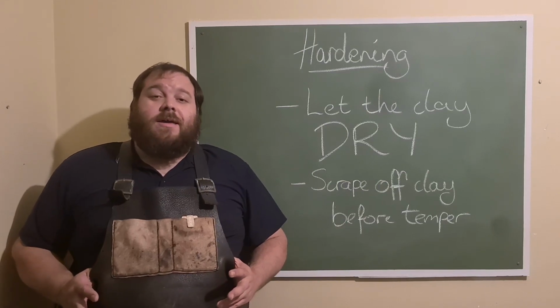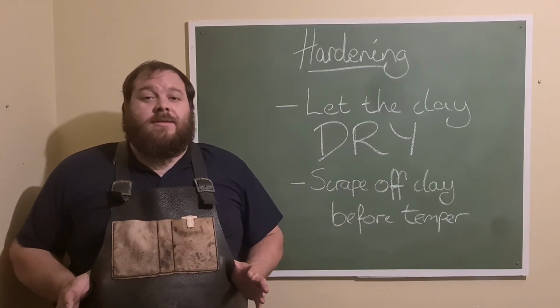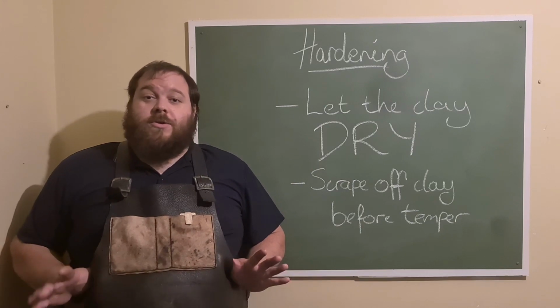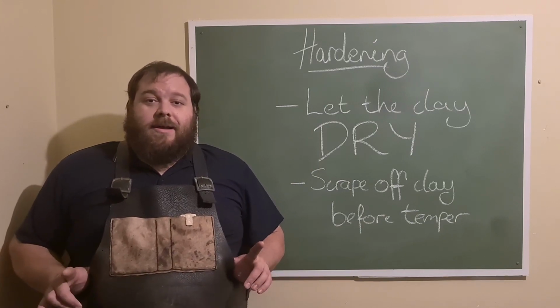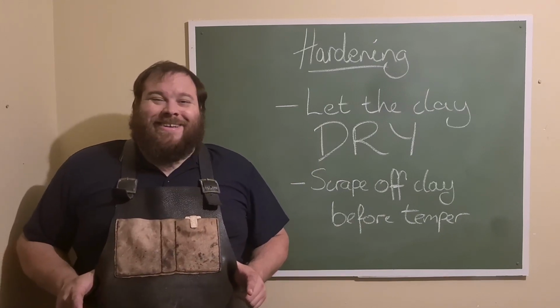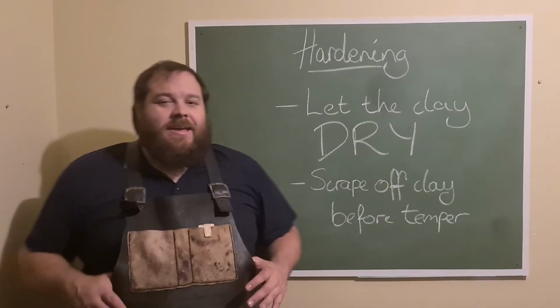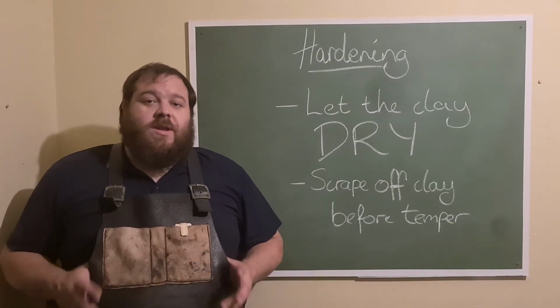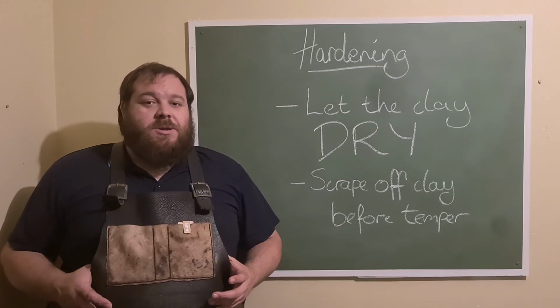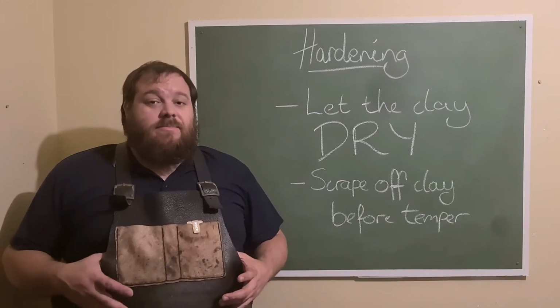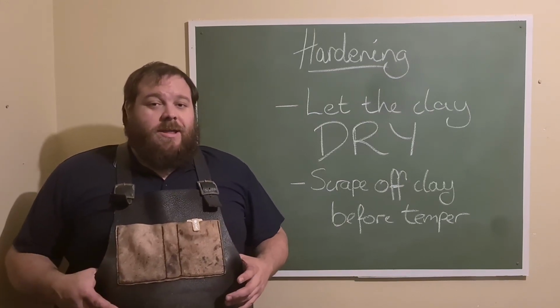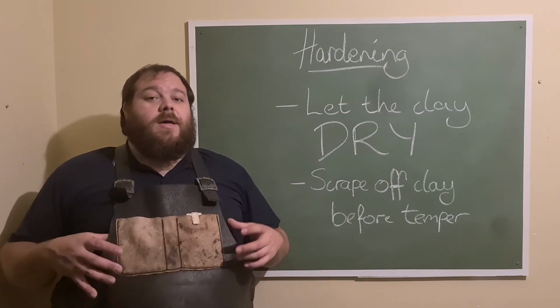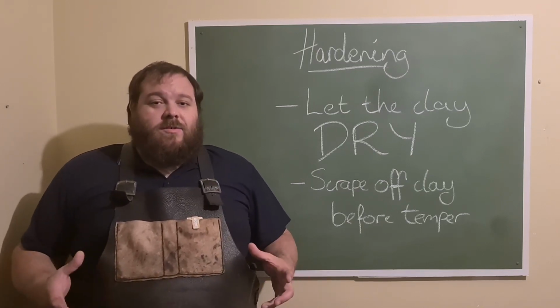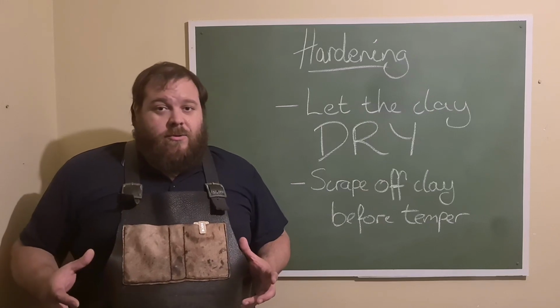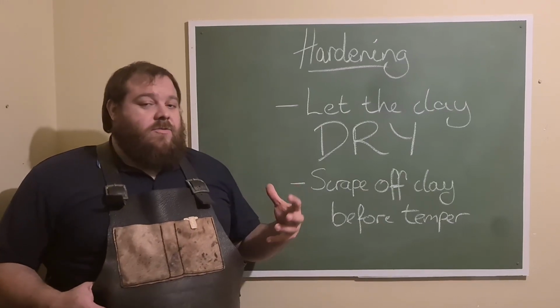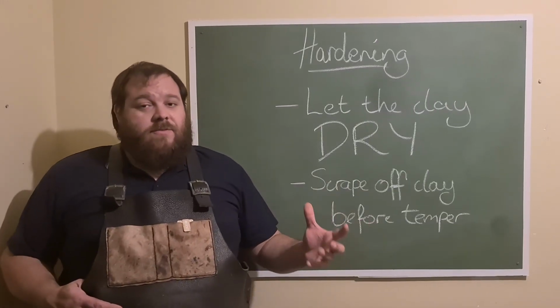You've applied your clay, you have your ashy lines cut in, everything is ready. What do you do now? Let the clay dry. Make sure that the clay is entirely dry before you start heating it up. Thermal expansion is a thing, and water steams off really fast. What'll end up happening is you will end up popping the clay off the sides of your blade before you even get it in the forge. So let the clay dry naturally, in light if you want to.